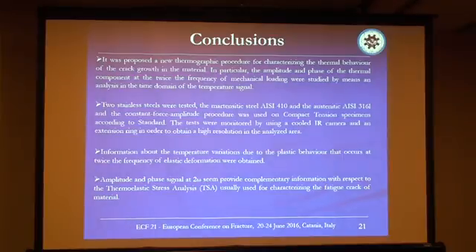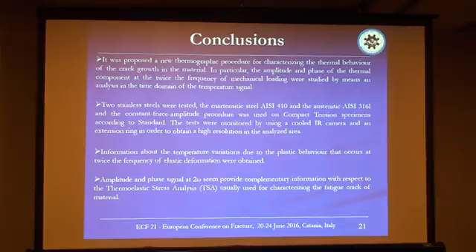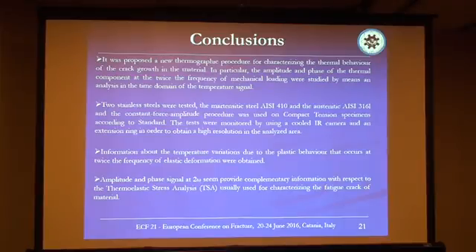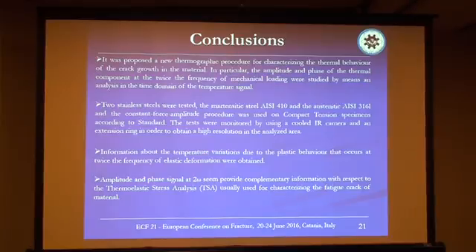In conclusion, a new thermographic procedure was proposed for characterizing the thermal behaviour of cracked material. In particular, the amplitude and the phase of the thermal component at twice the frequency of the mechanical loading were studied by means of analysis in the time domain of the temperature signal. Two stainless steels — martensitic and austenitic — were tested using a constant force amplitude process on compact tension specimens, with an extension ring added to obtain higher spatial resolution on the analyzed area. Information about the temperature variation due to plastic behaviour at twice the frequency of the elastic deformation was obtained, and the amplitude and phase signal at twice the loading frequency seem to provide complementary information with respect to the thermo-elastic stress analysis usually used for characterizing cracked material.